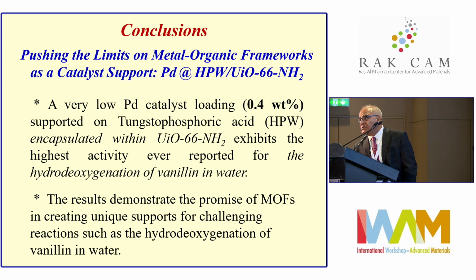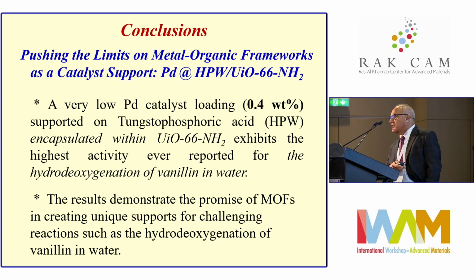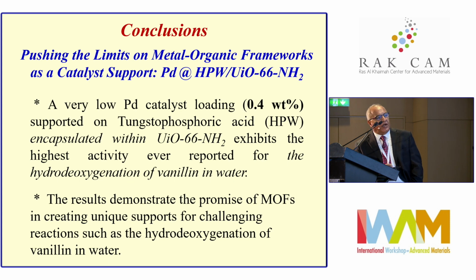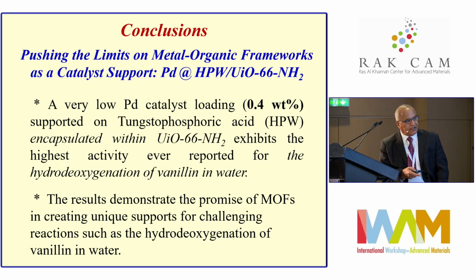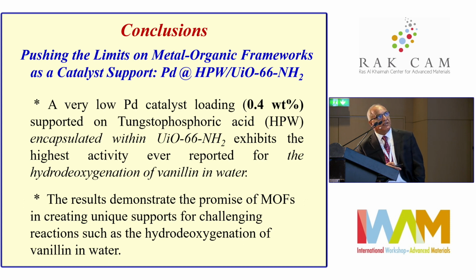And this is actually considered the highest activity for this reaction ever reported in terms of the concentration of the catalyst that we use. So the results here definitely illustrate the promise of the MOFs in creating unique supports for challenging reactions. This vanillin hydrodeoxygenation is one of the challenging reactions, and modification of the MOFs by incorporating the solid acid appears to solve this problem.